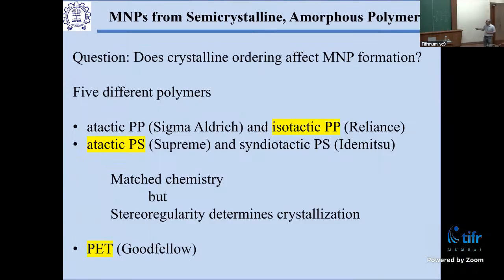And because we can get access to materials that are not commercial, we looked at comparing atactic polypropylene, which cannot crystallize, with isotactic polypropylene. This is commercial and it can crystallize. Atactic polystyrene, which is commercial but cannot crystallize, with syndiotactic polystyrene, which we can get, but this can crystallize, this cannot. So the chemistry is matched, right? So in terms of chemical attack, it should be the same, but then the stereoregularity determines whether or not it can crystallize. And also PET, but I'm not going to talk about that.